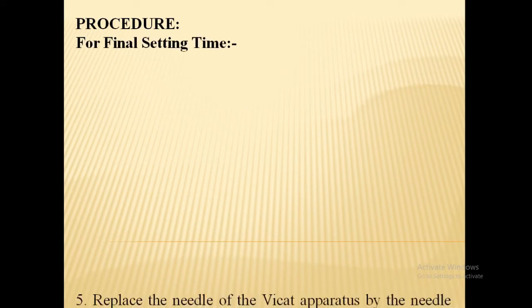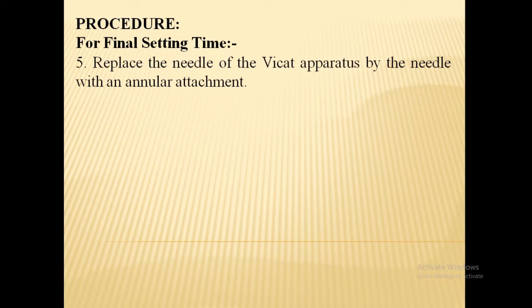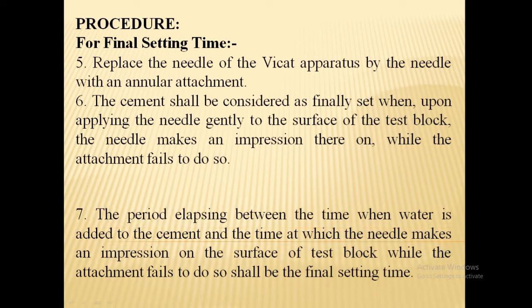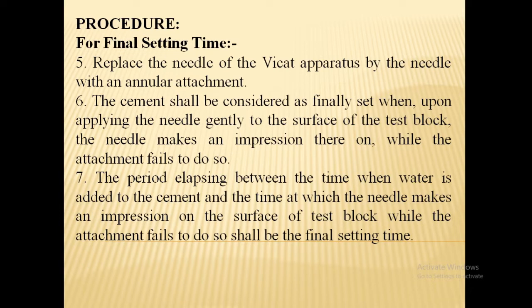For final setting time, replace the needle of the Vicat apparatus with the needle with an annular attachment. The cement shall be considered as finally set when, upon applying the needle gently to the surface of the test block, the needle makes an impression thereon while the attachment fails to do so. The period elapsing between the time when water is added to the cement and the time at which the needle makes an impression on the surface while the attachment fails to do so shall be the final setting time.